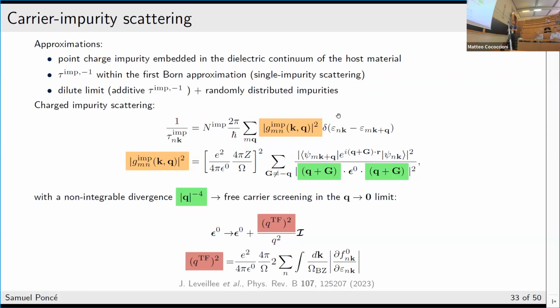Now, like I mentioned, there are different scattering mechanisms. I've dealt only with electron-phonon, but you also have carrier-impurity scattering. This is very important. If you start doping your material more and more, you will have basically interaction between the carrier that is propagating and the other excess carriers that you have in your material.